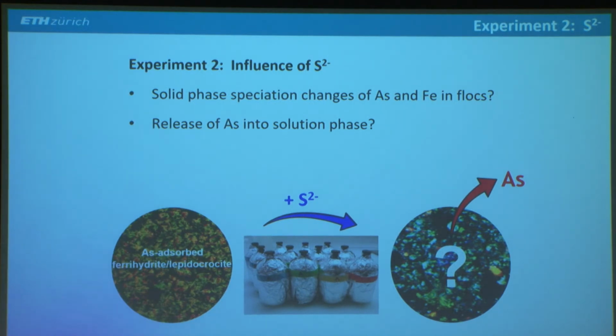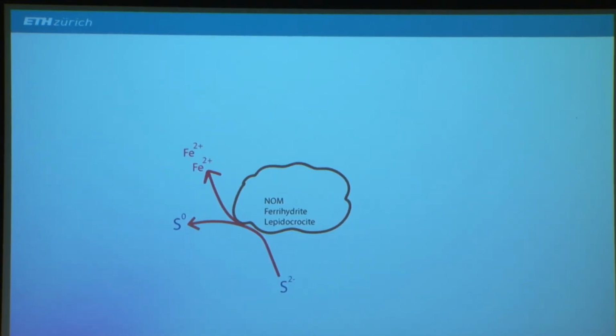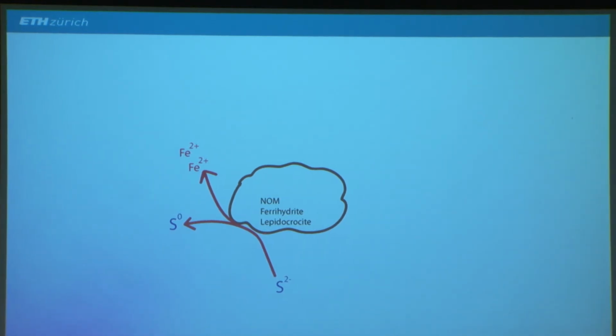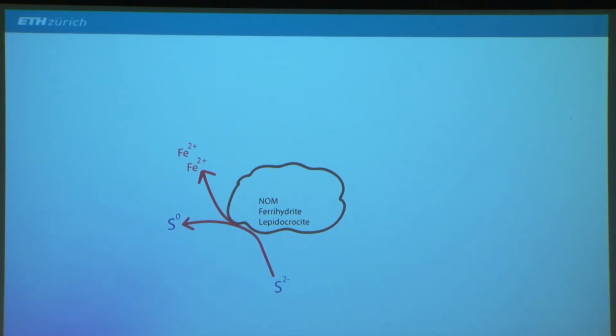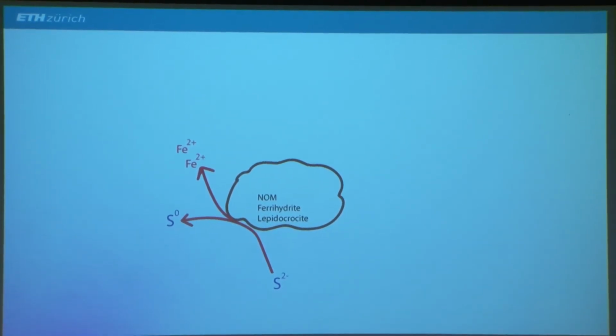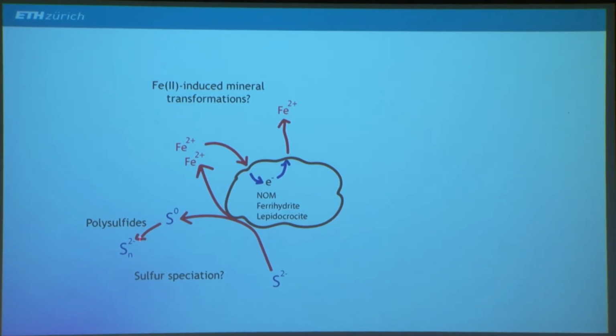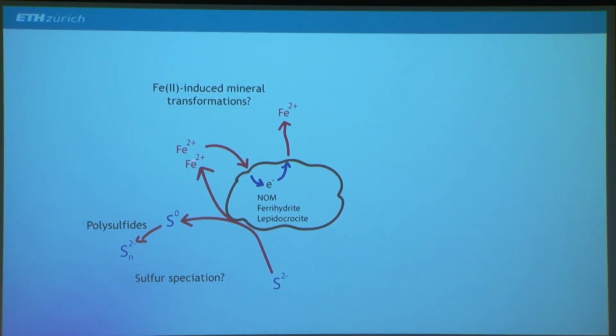So in the second experiment, it's the same idea. We took basically these flocks. This time we spiked sulfide and followed the speciation changes. So here, this system is significantly more complicated chemically, I think. And so what could happen is it's quite well known that sulfide can react with iron minerals to be oxidized to elemental sulfur, and the iron gets reduced to iron 2. This elemental sulfur can further react with additional sulfide to form polysulfides in solution. And the iron 2 could now drive mineral transformations, similar as I showed before.